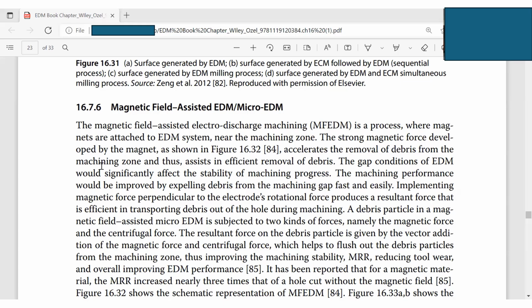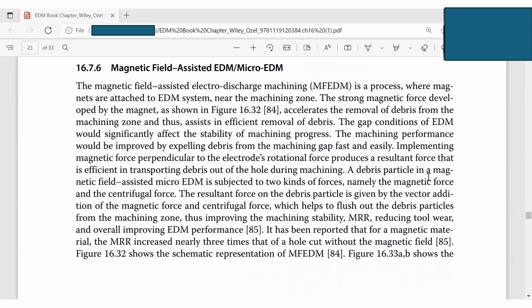The gap condition of EDM significantly affects the stability of the machining process. The machining performance would be improved by expelling debris from the machining gap faster and more easily, implementing magnetic force perpendicular to the electrode rotational force, which produces a resultant force that is efficient in transporting debris out of the hole being machined. A debris particle in a magnetic field assisted micro EDM is subjected to two kinds of force, namely the magnetic force and the centrifugal force.